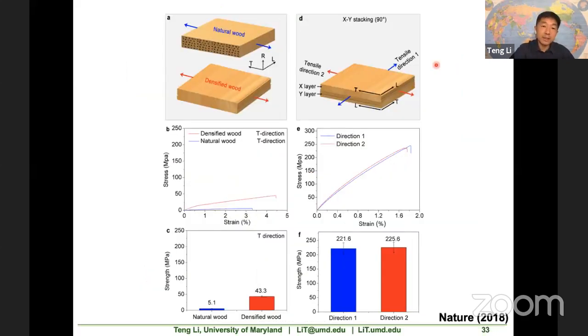And densified wood maintained the anisotropic behavior of natural wood. Which means that when you stretch perpendicular to the wood fiber direction, it is still weak. Although, as you can see in this curve, the red one is the densified wood. It's much stronger than the natural wood in the lateral direction, but it's low. It's around 50 megapascal.